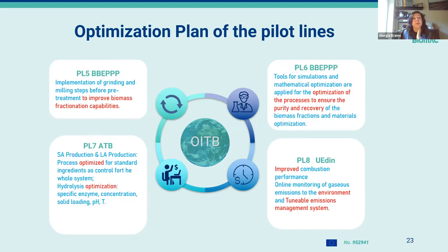Then pilot line 5, BBEPP, and pilot line 6 have 2 different objectives. In the first one, pilot line 5, implementing grinding and milling steps before the pretreatment in order to improve the biomass fractionation capabilities. Pilot line 6, utilizing tools for simulation and optimization, managed to optimize the processes to ensure the purity and recovery of the biomass fractions and materials optimization. Pilot line 7, ATB, is focused on the succinic acid production and the lactic acid production.